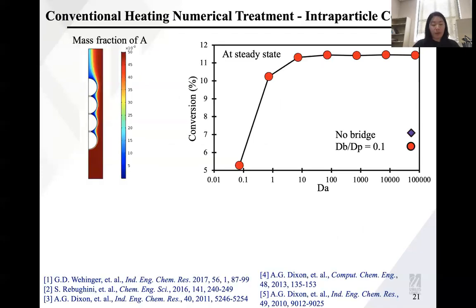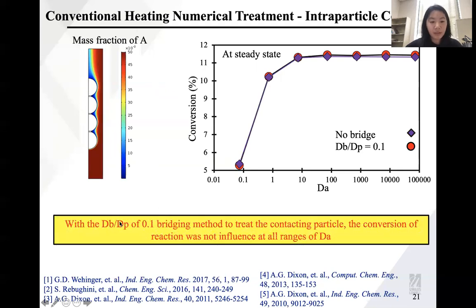When you have contacting particles inside your reactors, it's really hard to mesh for your simulations. The mesh will give you a really hard time to converge. So there are some numerical treatments for the contacting part in the packed bed reactor under conventional heating. The researchers add a bridge, and they found that when the bridge dimension relative to the particle dimension is around 0.1, the bridge method can treat the contacting particles' convergence issues. At the same time, it will give similar accuracy as compared to just having the particles touching each other.